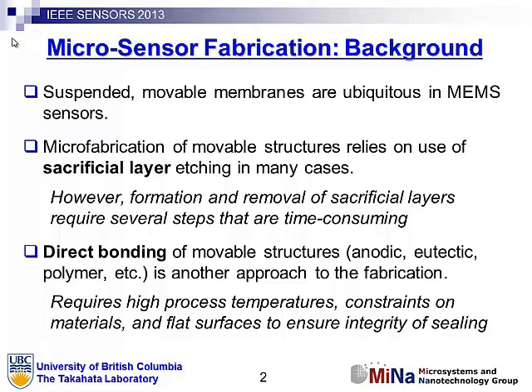And in all these methods, what's critical is that your substrates are very flat. So silicon wafers and glass substrates you'll find typically have surface roughness, say less than 10 nanometers. And that's what you need to get good bonding over the entire area. So that's the direct bonding method. And in the case of surface micromachining, you only need one flat substrate, but you'll use typically many photolithographic steps to create a sacrificial layer of either photoresist or SiO2, and the membrane over top of that, and then you'll release with either a wet etch or a dry etch afterwards. And this also can have some higher temperature steps, because there's usually PECVD deposition of membranes, and sometimes the sacrificial layer itself is also a chemical vapor deposition.